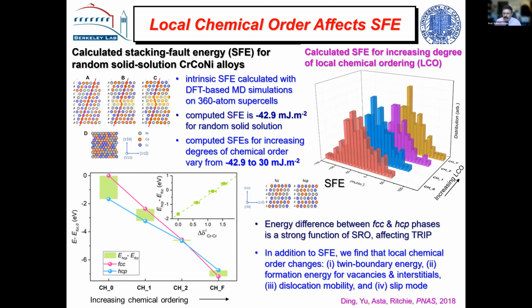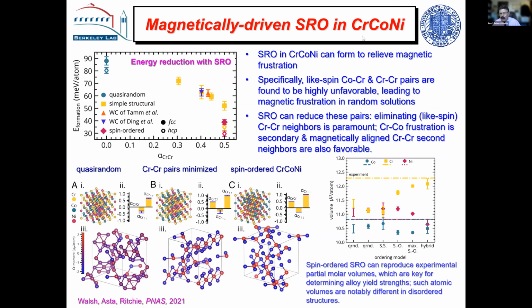The question is, is it really there? Yes, I think it is, but it may always be there. It may be ubiquitous. We don't know exactly. We don't know how to control it. That's the problem. But we think it may have an important role in developing this sequence of deformation mechanisms, which is so inherent to the properties. So one aside here, in this alloy, often the local ordering is associated with magnetism as well. If you put like spin atoms together, particularly chromium-chromium pairs, you get what's called magnetic frustration. So there's a magnetic component to the local ordering in these alloys as well.